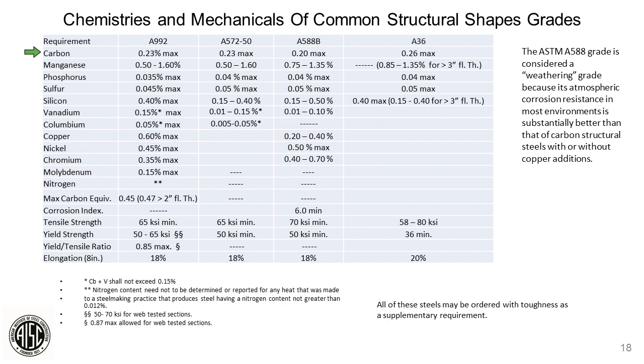So then we look at manganese next. That's a big one. It's a big addition. It's the biggest component of the alloying that we add in. So if you look at A992, it goes from 50 to 160. I'd dare say you're definitely about 1% on most stuff. Same with 572 and 588, about 1%. A36, you don't have to achieve the same strength levels. The manganese is typically lower.